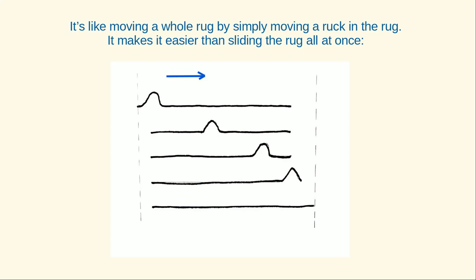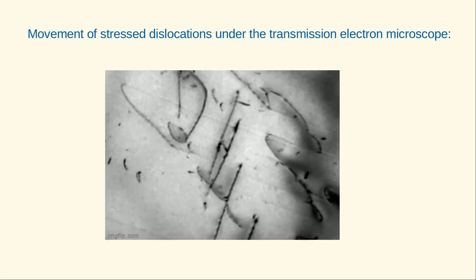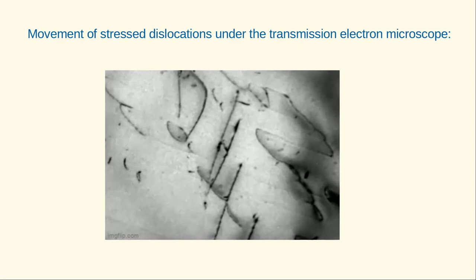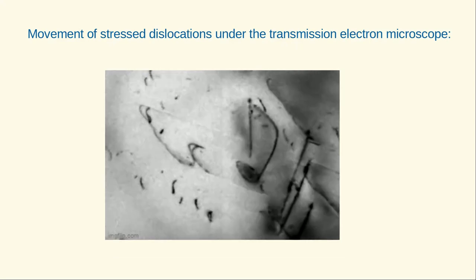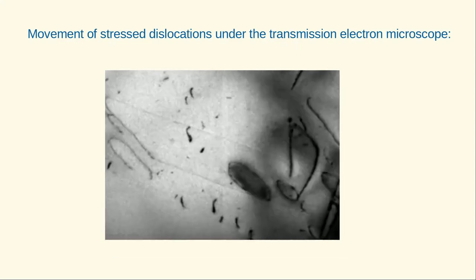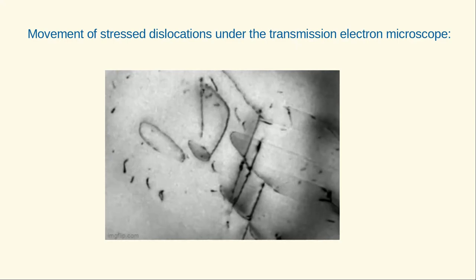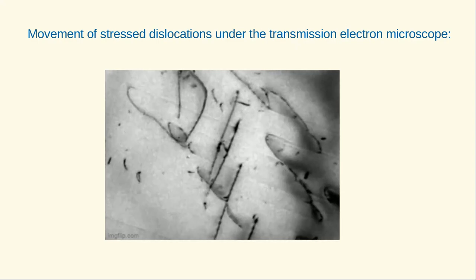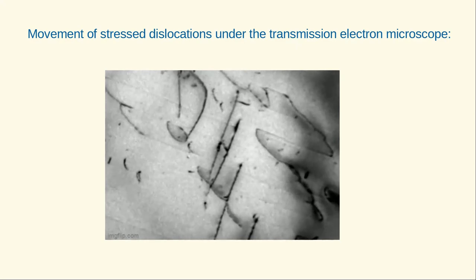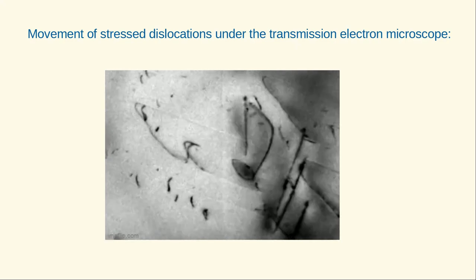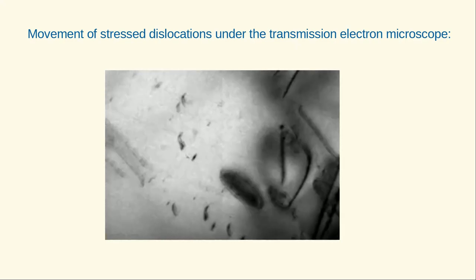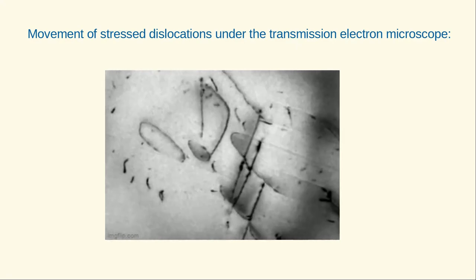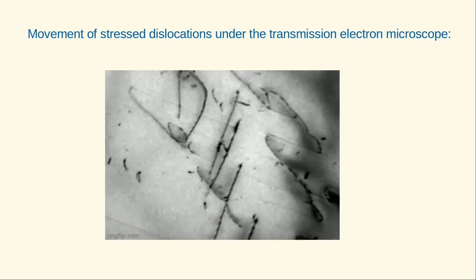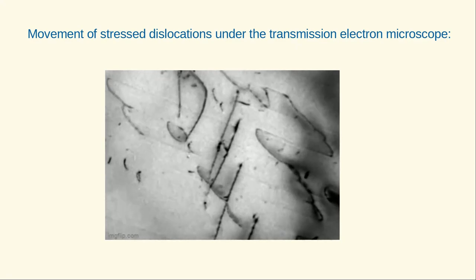What do dislocations look like? Well, under a transmission electron microscope, this is a stressed bit of metal, and the dark lines are dislocations, and they move because the stress causes them to move. And they're dark because that bit of lattice, that I showed you earlier, where it was stressed, where the extra bit of metal plane ends, that causes contrast in an electron microscope. In other words, it causes the electron beam to scatter, showing up as a dark image. And these images here show a dislocation or dislocations moving under the application of stress.